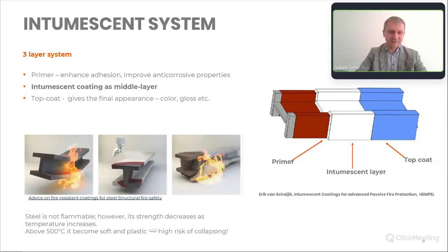And we reach the main question: why should we use a fire protective system on steel? Because the steel is not flammable. So why is it important, especially in industrial applications, to do that? Because even though the steel is not flammable, it becomes softened plastic after reaching 500 Celsius degrees. And as you remember, in case of hydrocarbon fire, we can reach it very rapidly. So you can imagine, for example, an installation and a fire on this installation caused by, for example, some combustible liquids. And within minutes, the whole installation can collapse. So there is no time for the evacuation, for emergency action, whatever.